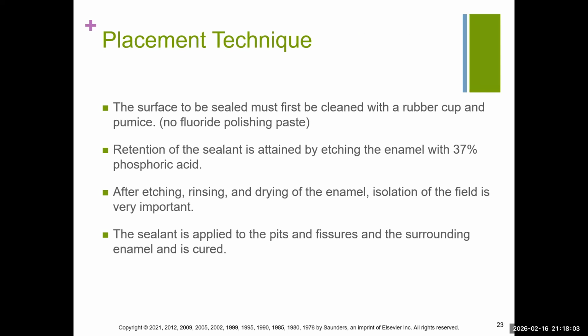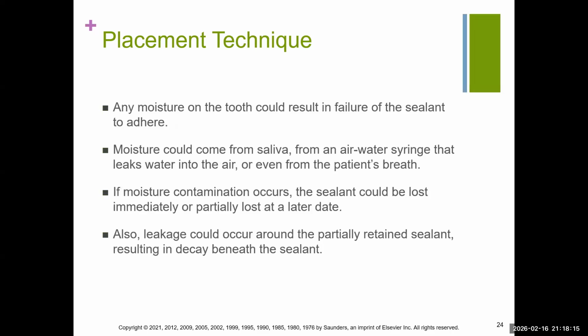So what are we looking for when we dry it? We're looking for a little bit of a frosty appearance, okay? And then you go ahead and apply the sealant in pits and fissures and the surrounding enamel and go ahead and cure it. Any moisture on the tooth could result in failure.